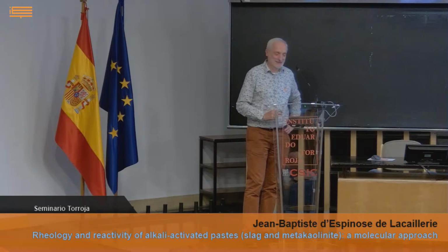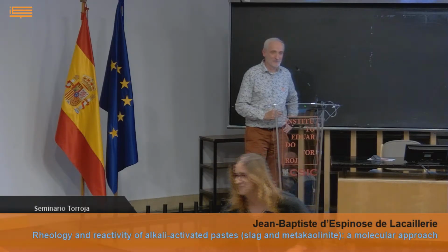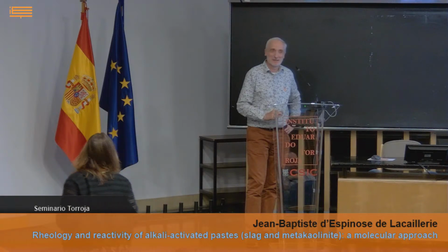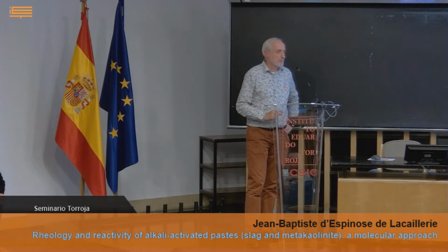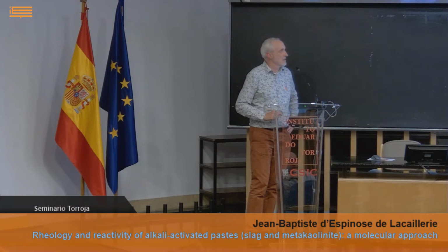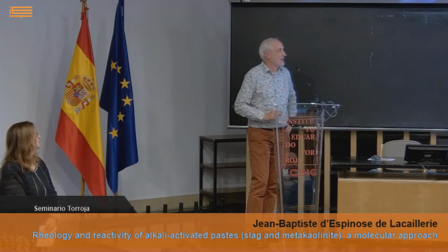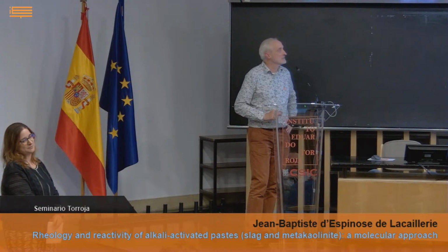Well, thank you, Jean-Baptiste. I'm happy to know what you're working on these days. It's very, very interesting. On slide 33, you use the Flory theory to measure the diameter or the hydrodynamic radius. The variation in diameter. Yes. But there are a few things here that I want to check, since I'm very interested in this type of technique. Did you take into account that your solvent viscosity was changing because of the ionic concentration?